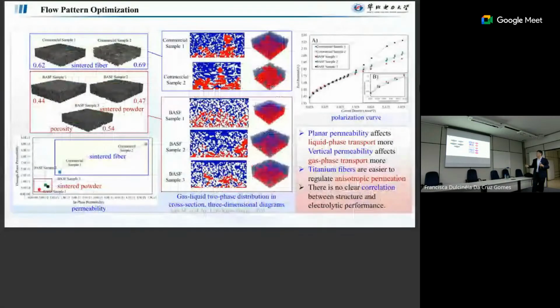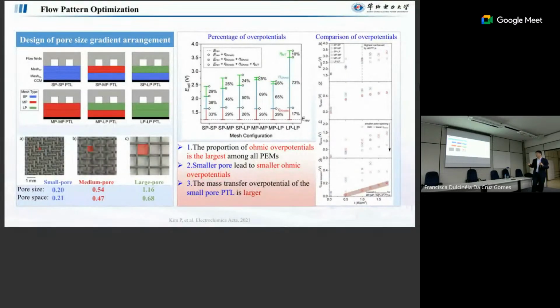The good thing here is that when we use these fiber-based structures, we can tune the in-plane transport and the through-plane transport ourselves. That's also a good concept from the paper. Then people studied different gradients, for example gradient alignment, and they also got some data. But for me also, it's difficult to say which is good. In the end, they tried small pores, medium pores, and large pores, and they got some good results.